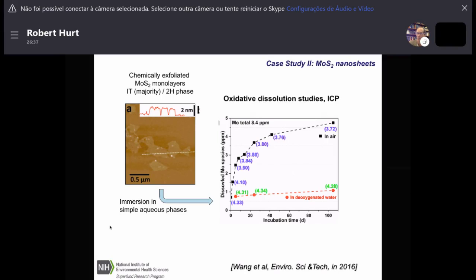But we've found, and others have also been finding, that it's not fully stable over time in the presence of oxygen. Living things need oxygen to metabolize, as oxygen's ubiquitous in the human body, and molybdenum disulfide, if put in biological simulant fluids, undergoes a slow dissolution. This graph shows that over 100 days, this material will slowly degrade, and the molybdenum will appear in solution as a dissolved product. The nanosheets will be destroyed.